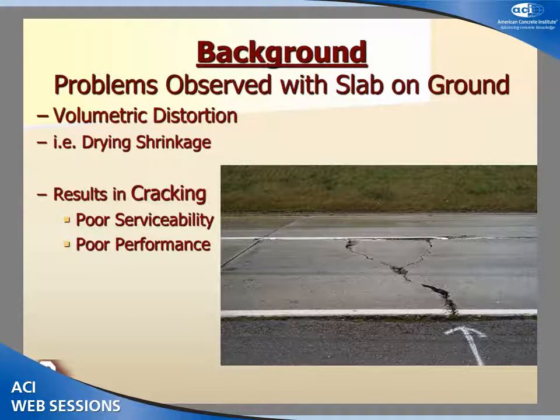About 2/3 of all the concrete in the world is used as slabs on ground, and many problems are encountered in practice with slabs on ground. As a huge amount of concrete is used as slabs on ground, maintenance becomes a concern. One of the major causes of the maintenance needs for slabs on ground is the volumetric distortion of slabs, which is commonly caused by drying shrinkage. Drying shrinkage results in cracking in the concrete, and if drying shrinkage is not controlled, it can lead to serious serviceability problems and performance problems.